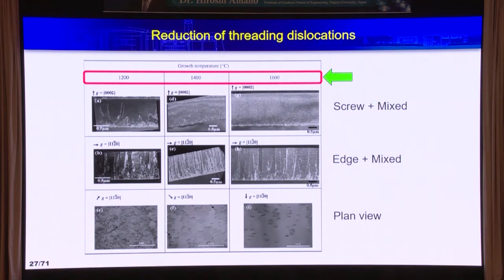Okay, first, to grow high quality aluminum gallium nitride, we need high temperature growth. This is the dislocation, the defects. With increasing growth temperature, dislocation can be minimized. That's the first point.